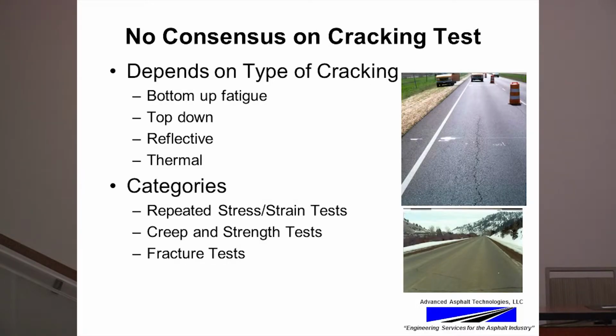With respect to the cracking tests, unfortunately, what I can report to you is that there really is no consensus on a cracking test. Okay, and I think there's a couple of reasons. One is the cracking mechanisms that occur in pavements are much more complex compared to the rutting problem that we have. You've got different modes of cracking. So you can have bottom-up fatigue cracking, top-down cracking, reflective cracking, thermal cracking.